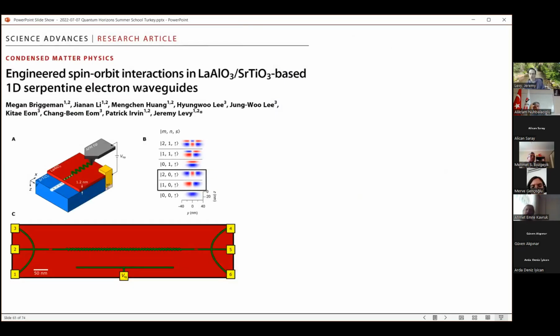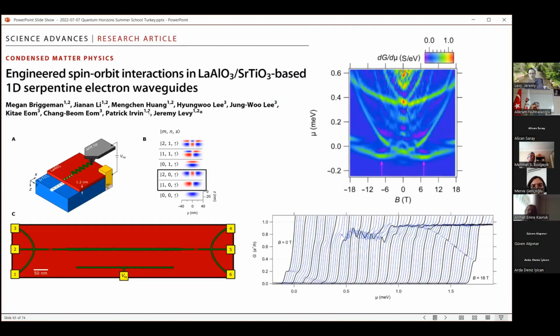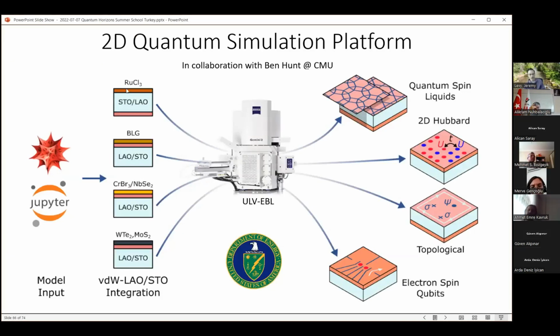We can also engineer spin orbit interactions, and we do this by causing a meandering of the wires just by moving the tip back and forth. That acceleration as the electrons move back and forth engineers a periodic spin orbit interaction, which also modifies the electronic band structure in a fundamental way. One of the things that we're doing right now, this is an active program, is to integrate these materials with other systems like two-dimensional van der Waals layers, like graphene, bilayer graphene, ruthenium chloride. And so the idea is to imprint electrostatically new interactions on interesting and existing materials.